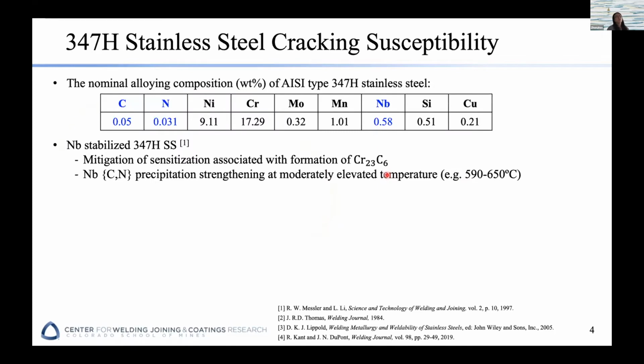So first of all, let's see what the composition of this stainless steel is. In addition to those typical compositions that you would see in other materials, we find that they add niobium and nitrogen intentionally. The reason is to form niobium nitrides instead of forming chromium carbides. If chromium carbides form, it will typically take out the corrosion resistant element chromium, and that will cause a well-known problem called stress corrosion cracking. So by adding niobium and nitrogen, you can form niobium carbon nitrides that also serve as a precipitate that strengthens the material at the moderate elevated temperature between 590 and 650.